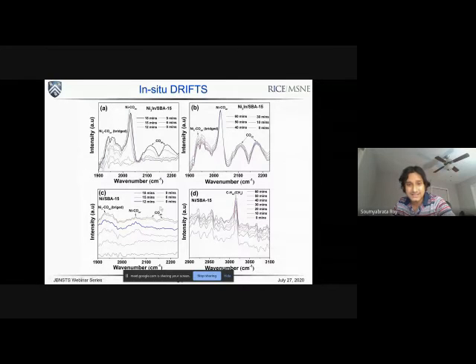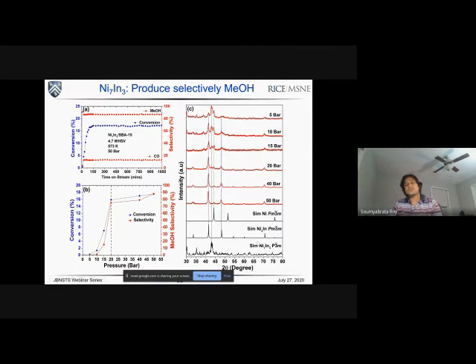So here we can see that in the case of just the nickel catalyst, we could only identify the carbon monoxide stretching, while in the other case, we could actually see the CH stretching of methane, which tells us at what point in time methane production starts forming, which we can correlate to the formation of the second phase that I showed you.